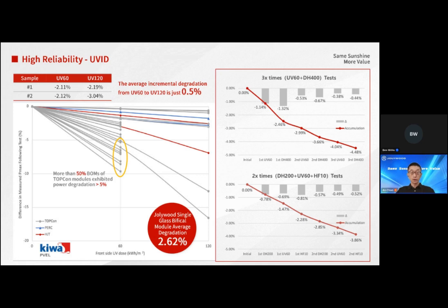In addition to these results, we also conducted more rigorous combination UV aging testing in our own lab. After 3 times UV60 plus damp heat 400 test, the module's power degradation was just 4.48%, and after 2 times DH200 plus UV60 plus HF10 test, the degradation was only 3.86%. These findings demonstrate the excellent long-term UV resistance of the Jolywood module, ensuring its stability and reliability under UV exposure.